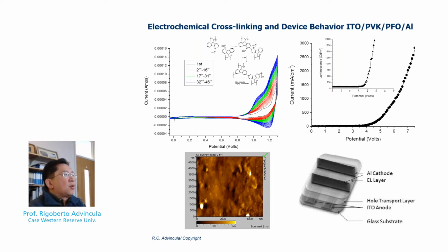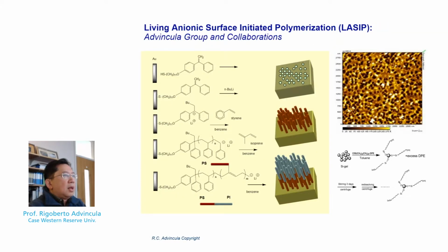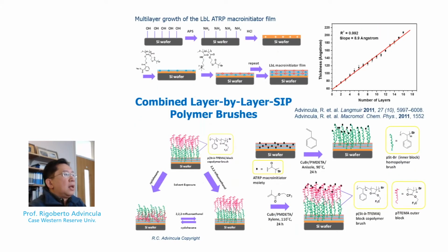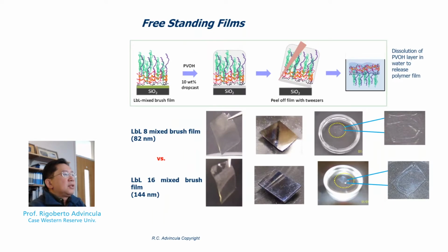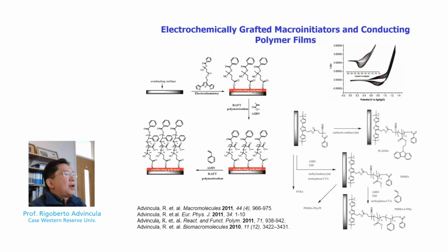So after cross-linking the vinyl carbazole units on the polymer brush, this resulted in a lower turn-on voltage as compared to a non-modified ITO surface, for a device structure made up of PVK as a hole transport layer, polyfluorene as the active blue emitting polymer, and then aluminum as a cathode. So let me skip some of these slides to focus on patterning.